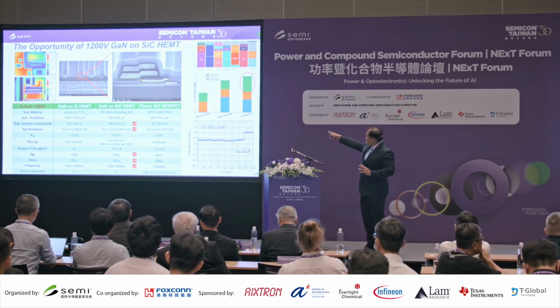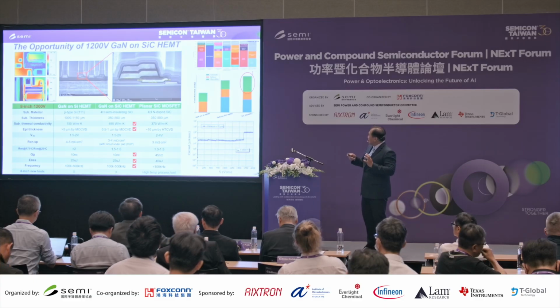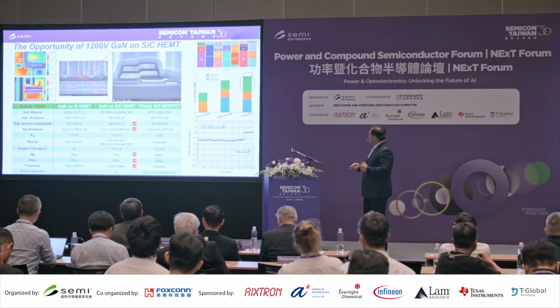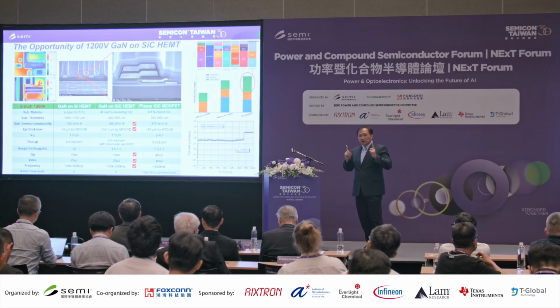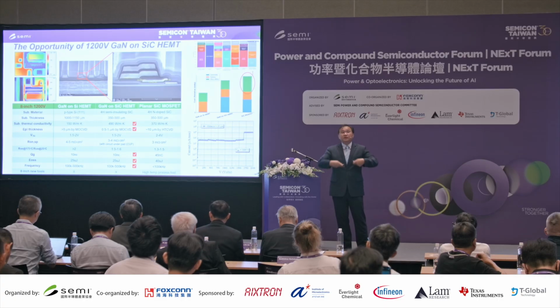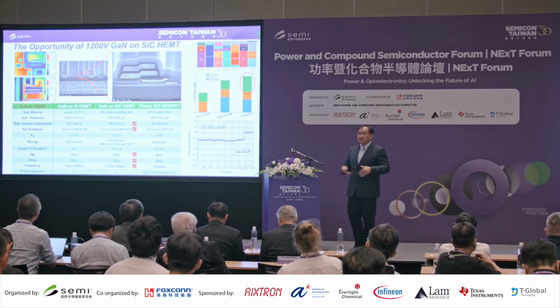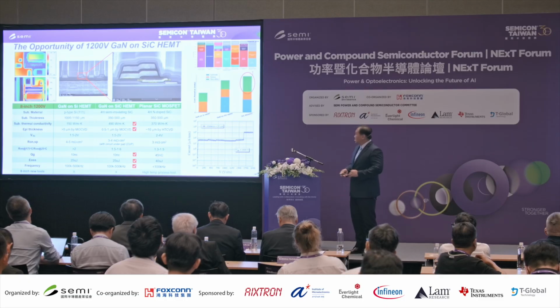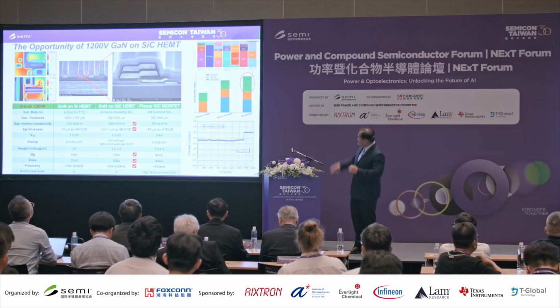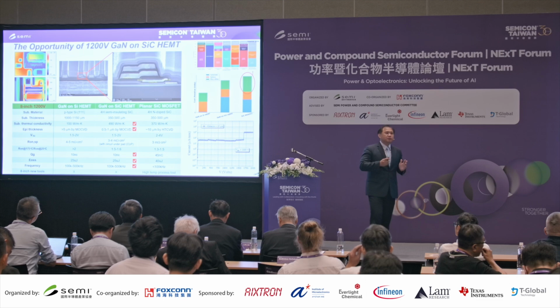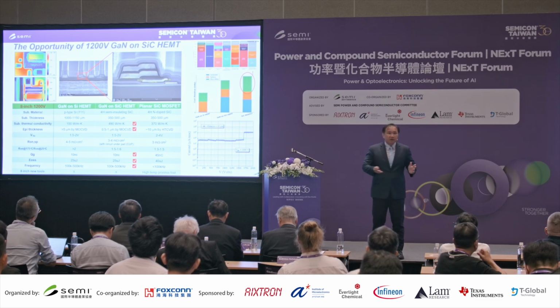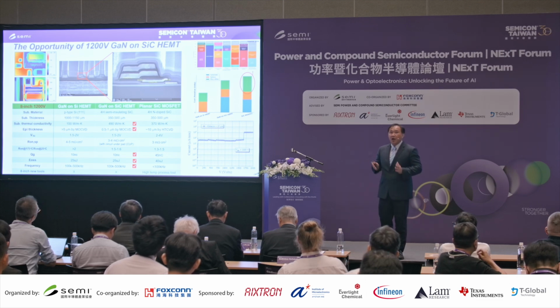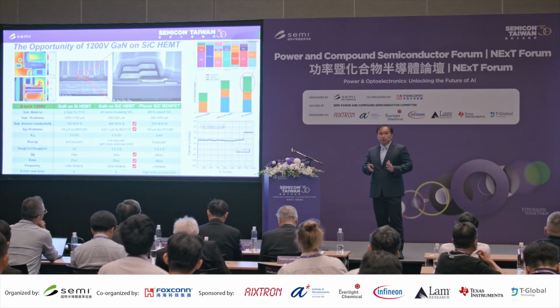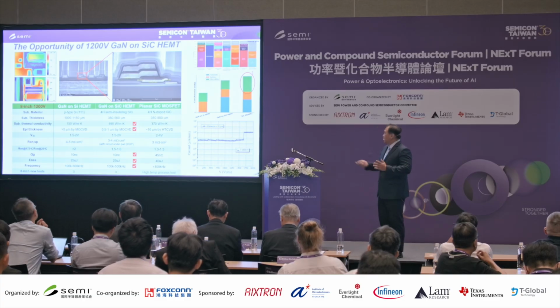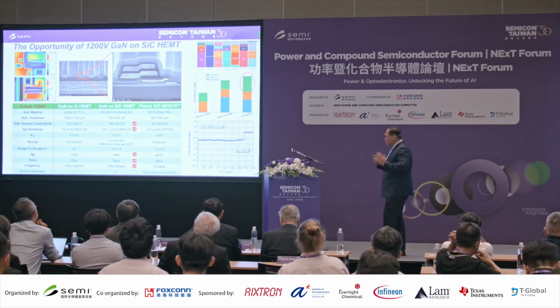So I just show you one picture comparing silicon carbide substrate cost. For the epi growth, similar. But one key issue happened. Because in Taiwan, for GaN on silicon carbide, you can submit the wafer to the foundry backend service directly, because of the gallium nitride. But for silicon carbide, I referenced one picture. You need to purchase the high temperature implanter, high temperature oxidation, and at least in Taiwan, you need to pay 3 billion Taiwan dollars to add some high temperature equipment for the 1200 volt silicon carbide device.